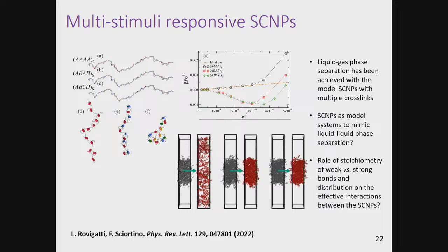So in this work, what is basically found is that if you increase these different types of reactive monomers, the kind of structures you get are more compactified, simply because of the same contour distance logic. They need to find their partners at longer distances, so they fold more effectively as compared to the homo cross-linking case.